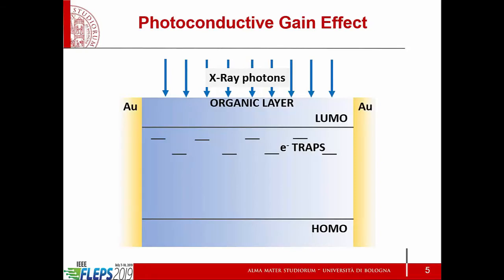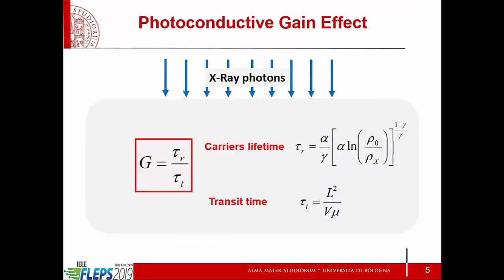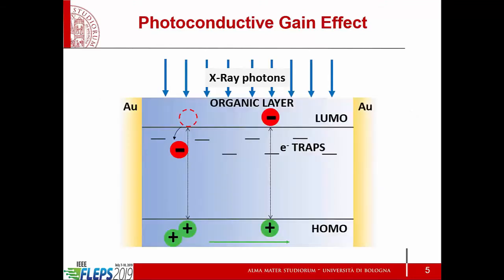What is this effect? It's known also in the organic photodiode community. When X-rays arrive onto a thin organic small molecule film, basically they do generate electron hole pairs, but the films contain a large number of traps, in particular electron traps, that make the material, usually in this case TIPS-pentacene, a p-type conductor. And so electrons are trapped and holes need to be constantly emitted from the source to the drain in order to maintain charge neutrality. And so what happens is that as long as the electron stays trapped, we have a gain induced by the extra number of positive charges that have to be injected again to maintain charge neutrality.